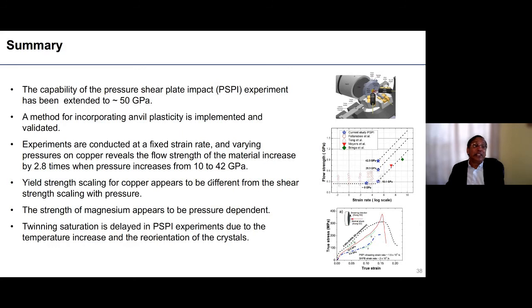Also, the yield strength scaling for copper appears to be different from the shear strength scaling, which is assumed to be the same in the literature. And I showed you very briefly that the strength of magnesium is pressure dependent, and there are very interesting mechanisms which operate in magnesium, because of the temperature increase and the reorientation of the crystals.